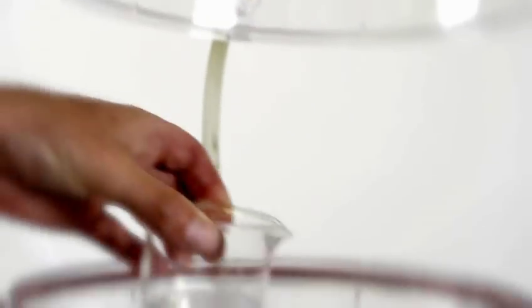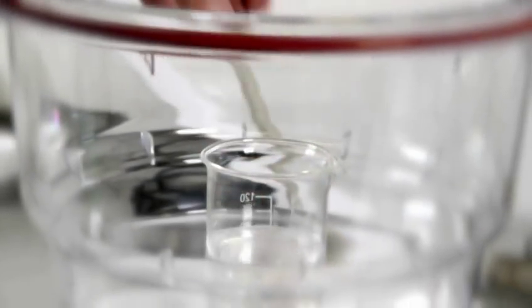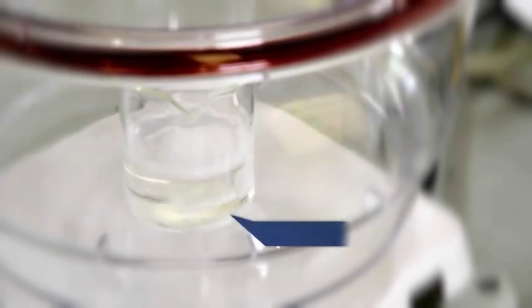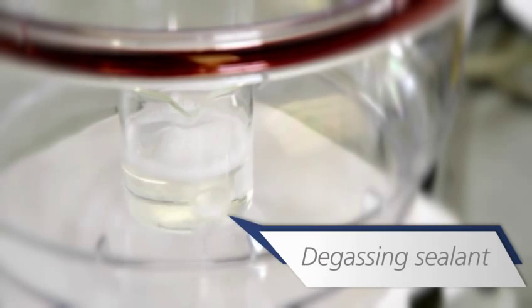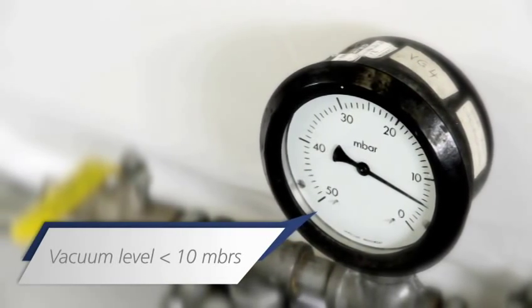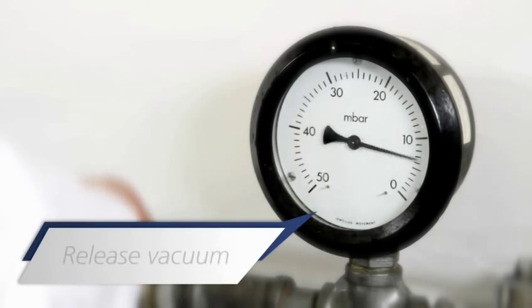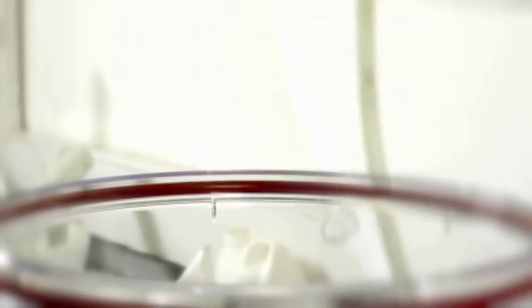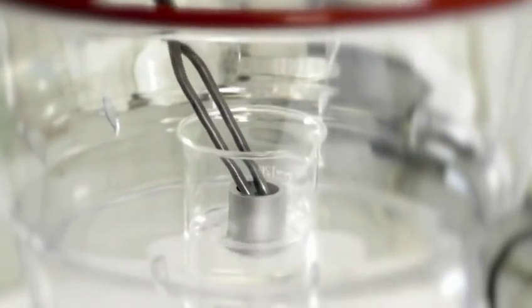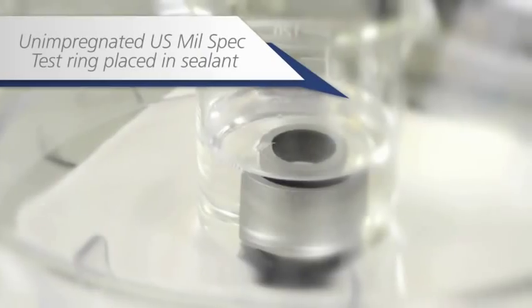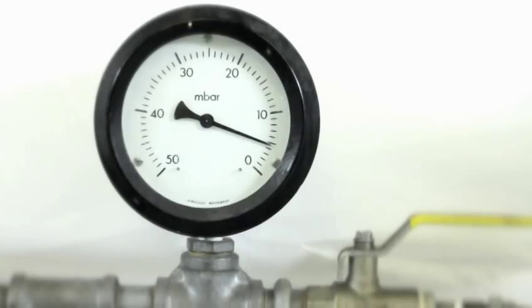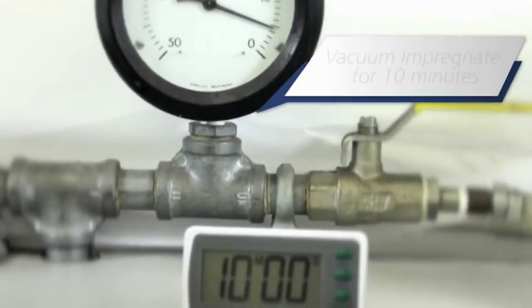We prepare a sample of one of our innovative sealants by applying a vacuum to it to remove dissolved oxygen. We then introduce the test ring to the sealant and again apply a vacuum. The sealing process now begins and for this test, we would leave it for 10 minutes.